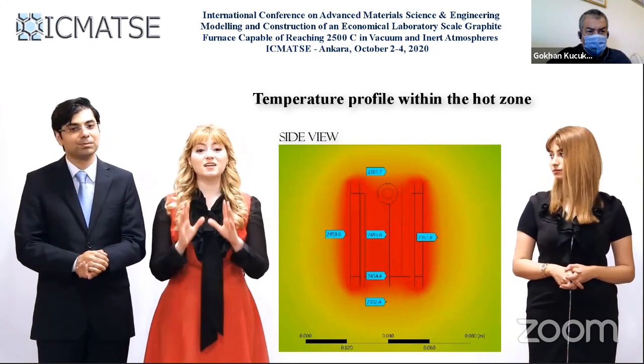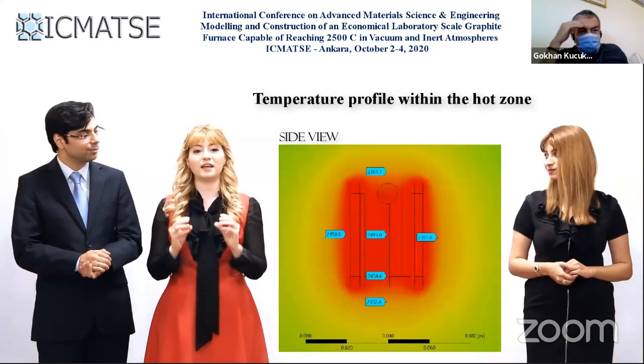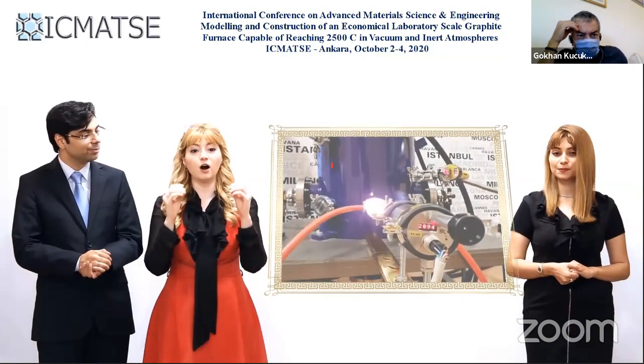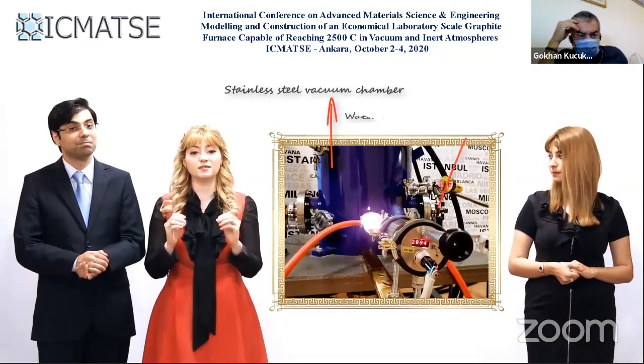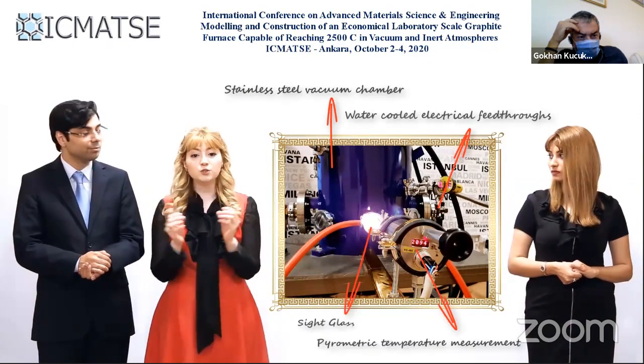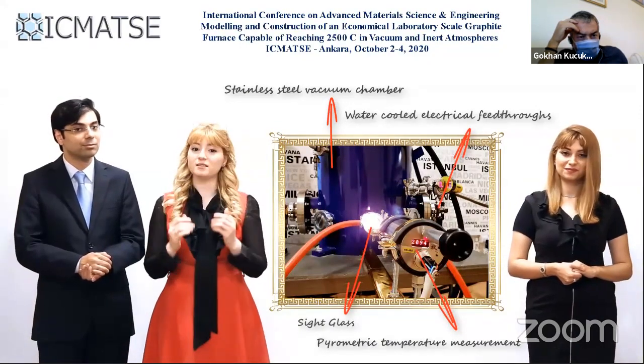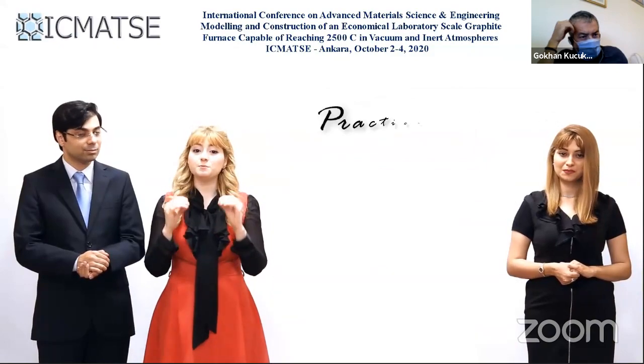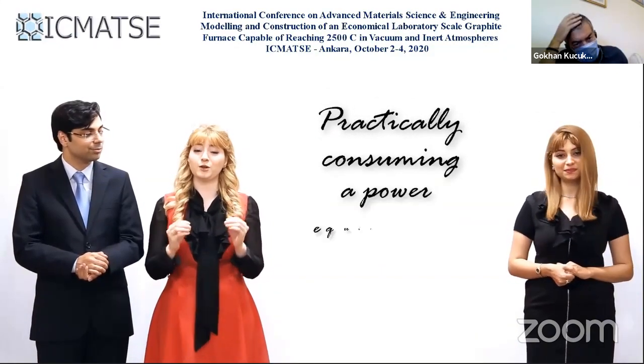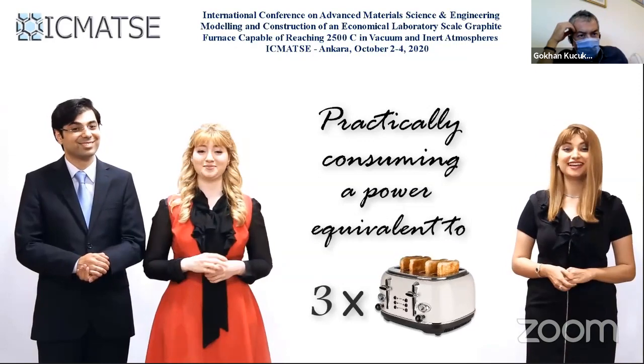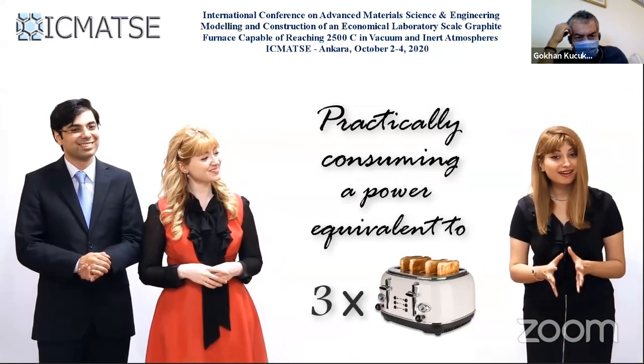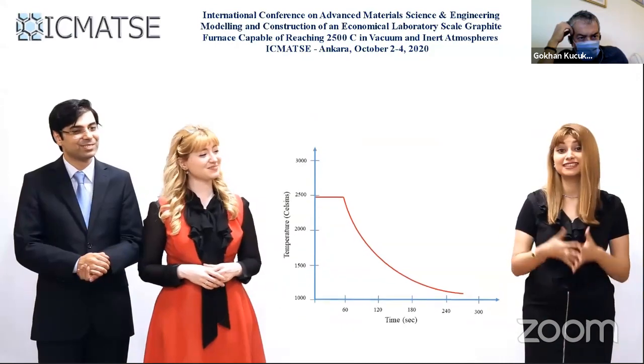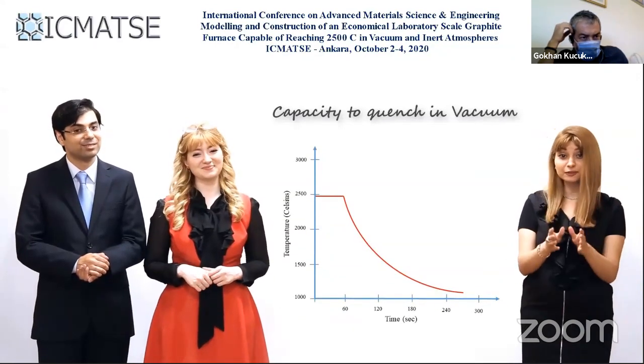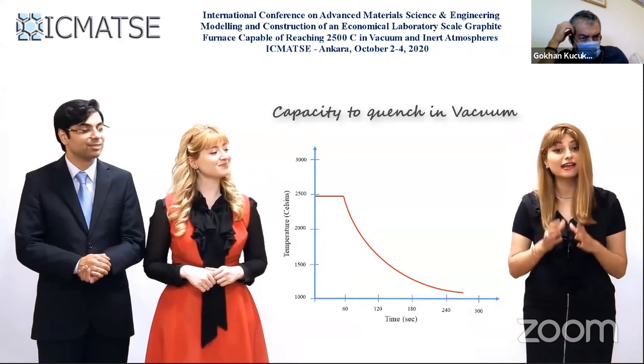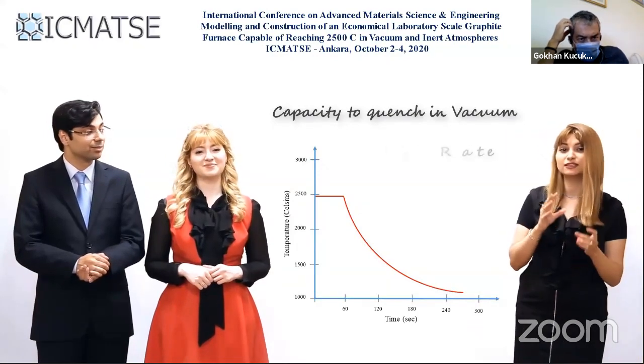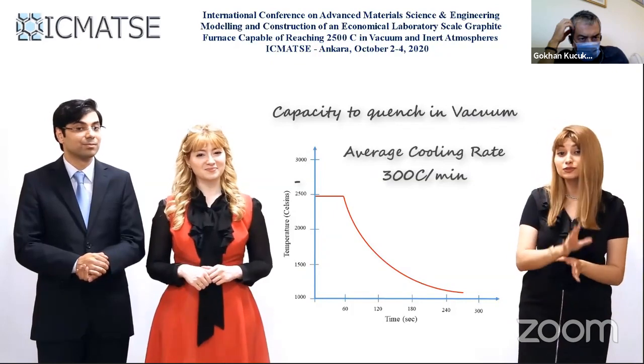The entire system works on single-phase alternating current, with the hot zone placed inside an ordinary vacuum chamber with two water-cooled electrical feed-throughs connected to a stainless steel chamber. And the entire system is practically consuming a power equivalent to 3 toasters. Another beauty of this design is that due to its size, the water cooling system has the capacity to cool it down very effectively if the power is disconnected. And we have seen an average cooling rate of approximately 300 Celsius per minute, from 2,500 to 1,000 Celsius.